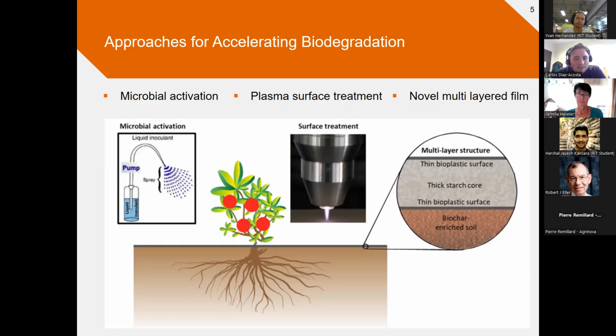The second approach is more of a physical approach. We know that the biodegradation starts at the surface. The microbes need to adhere to the surface. So we borrow a known technology from the packaging industry. And we said, what about we do a surface activation treatment using plasma? Why don't we pre-treat or pre-degrade just the very surface of the film without compromising the mechanical properties, and in that way increase the wettability and the adhesion of microbes? So we're going to hear about that as well.